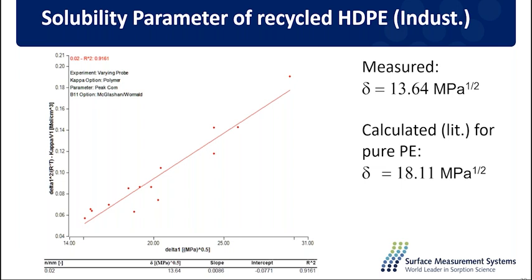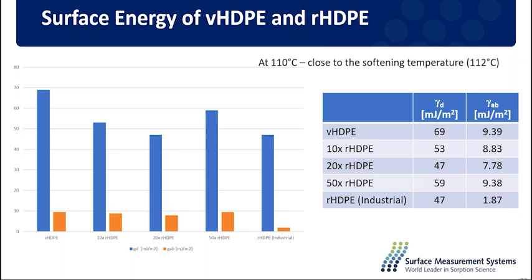And we are still working on the other samples to get the solubility parameter, but we have a good trend on surface energy, because we first measured the surface energy. I think it's just this I did as a last slide. So the trend is quite clear. So the virgin HDPE has quite high surface energy, and then the 10 and the 20 times recycled show decreases in surface energy. But then the 50 times recycled HDPE has again a little bit higher surface energy, whereas the additional measurements, some rheological and other data, showed there's more degradation happening. So these are the results so far that we have on polymers.